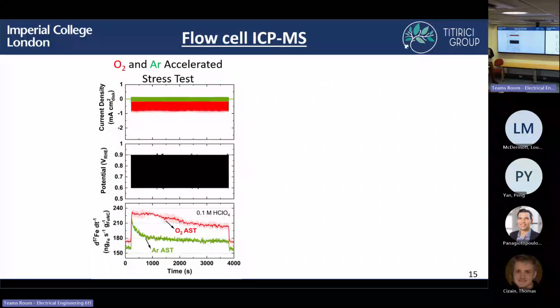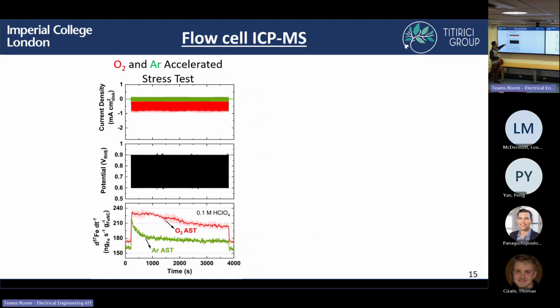But the interesting thing is, if you then do an accelerated stress test, so you're sweeping the potential from 0.9 to 0.6 volts, holding it 3 seconds at those potentials, you see something a bit different. You see that in oxygen, we have a greater iron dissolution compared to argon. And you can see as well, again, as you expect, a slightly higher current density in oxygen as we're converting oxygen to water.